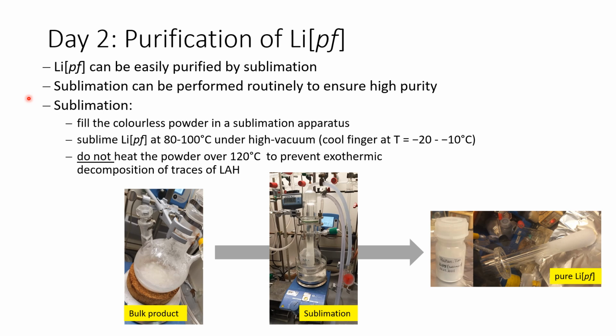If we have seen some impurities in our end product and want to ensure a very high purity, which is especially needed for electrochemical applications, we can easily sublime the lithium salt. To do that, we fill the colorless powder under inert atmosphere into a sublimation apparatus, and then we sublime the product at 80 to 100 degrees under a dynamic high vacuum. Here it is good to cool the cooling finger to -20 to -10 degrees Celsius to ensure that the product does not fall off the cold finger when we dismantle the sublimation apparatus.